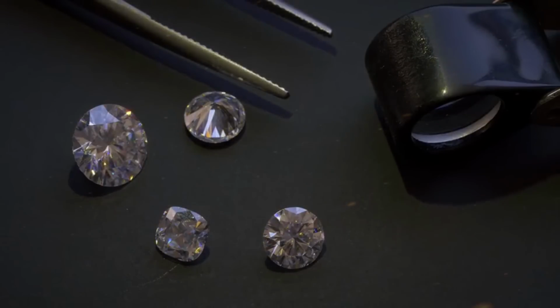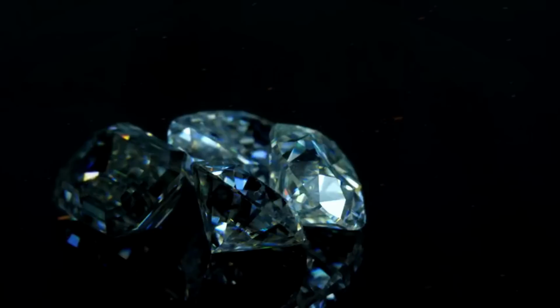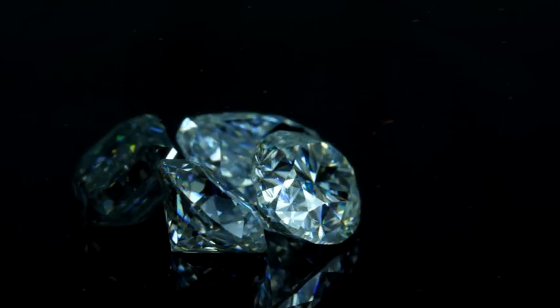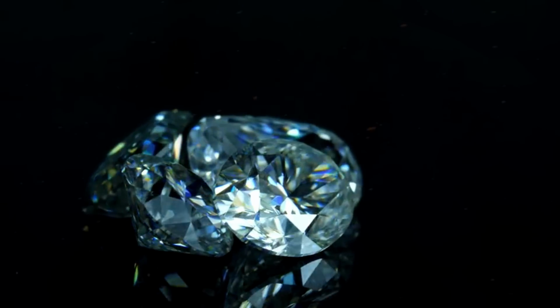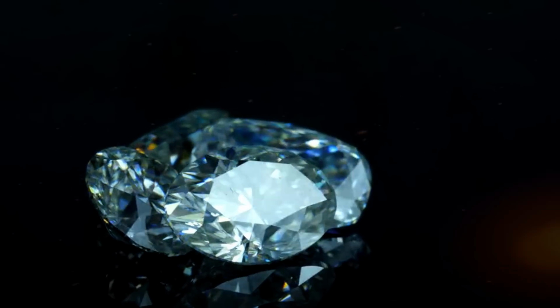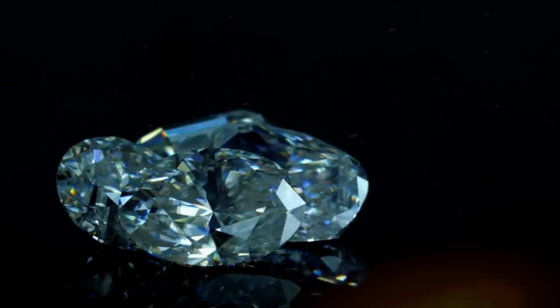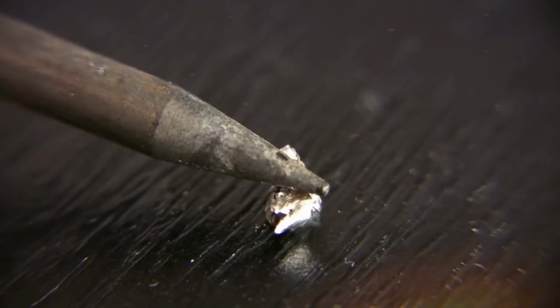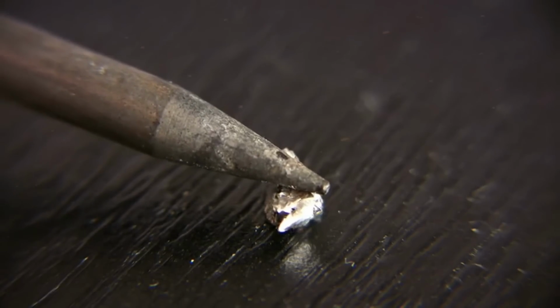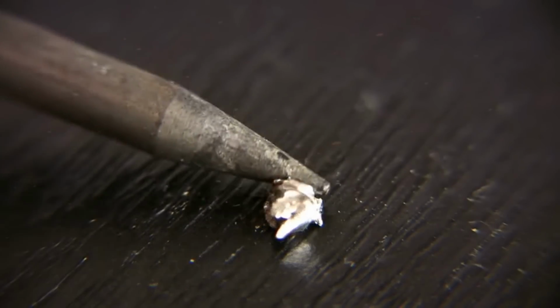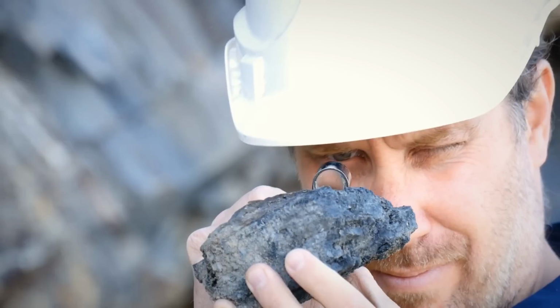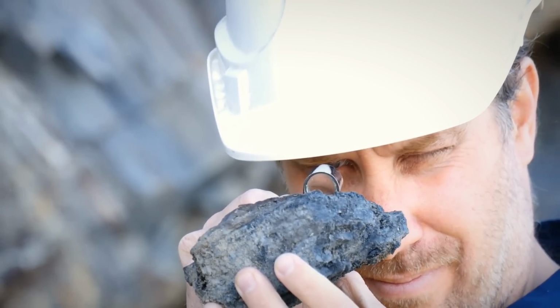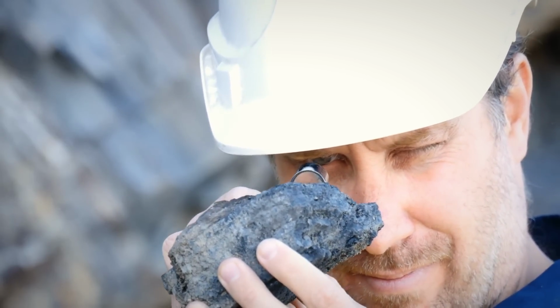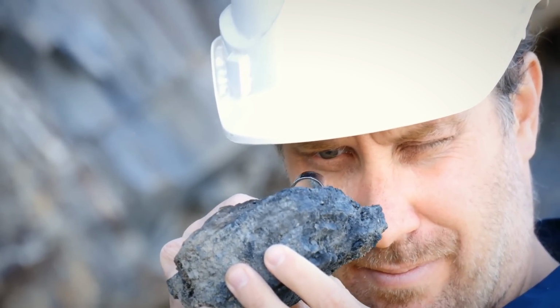Once the core is exposed, immediately begin second-tier diagnostics. Start with the conductivity probe, thermal and electrical. If the thermal conductivity test reads positive and electrical reads negative, that's strong evidence for diamond. If both light up, moissanite is likely. No signal on either? You're probably dealing with zircon, quartz, or an artificial byproduct.